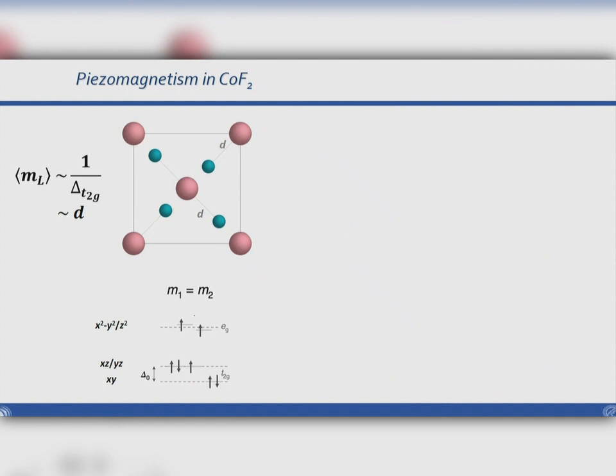And why is this so? What one knows is, this is a D7 system, and the orbital contribution to the local magnetic moment on each site is proportional to the inverse of the energy splitting of the T2g bands. And this is linearly proportional to the distance d between the cobalt and the fluorine atoms that you have in this compound.